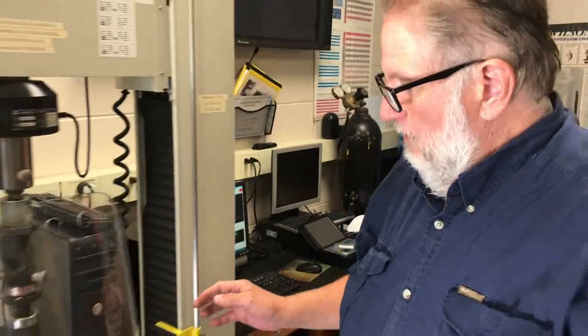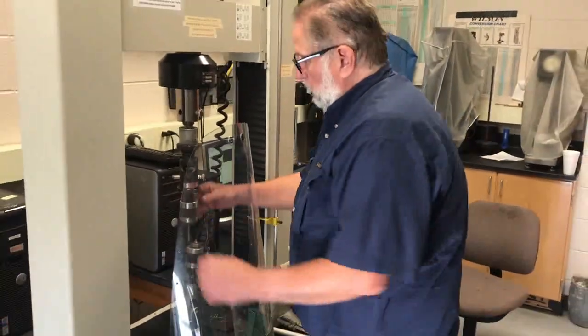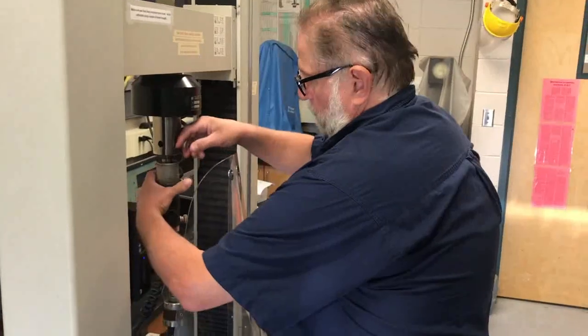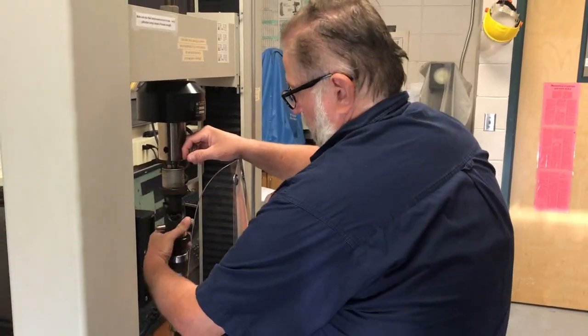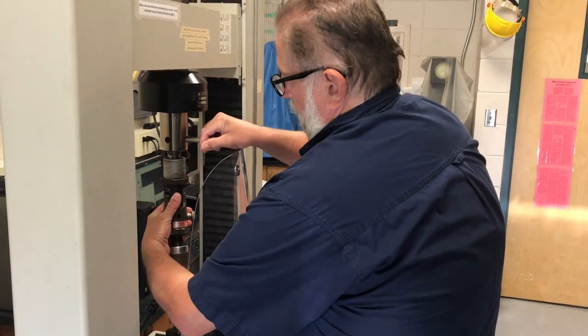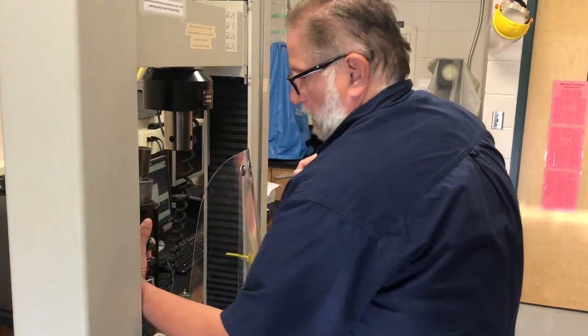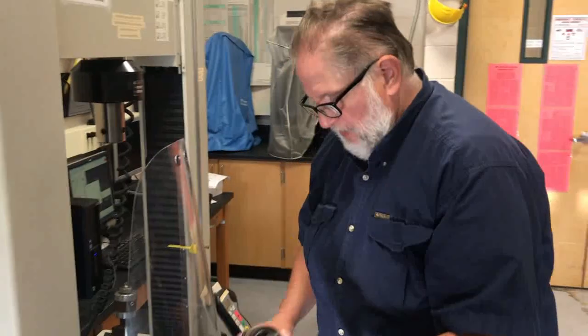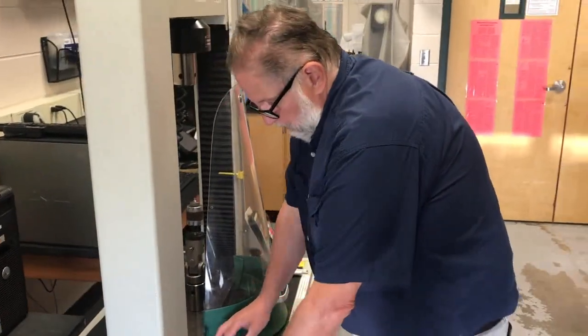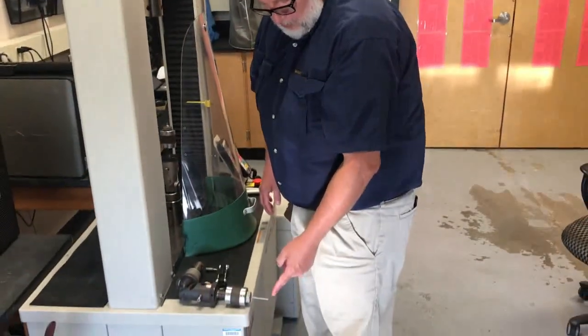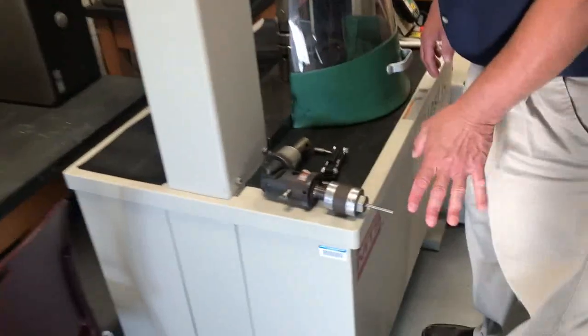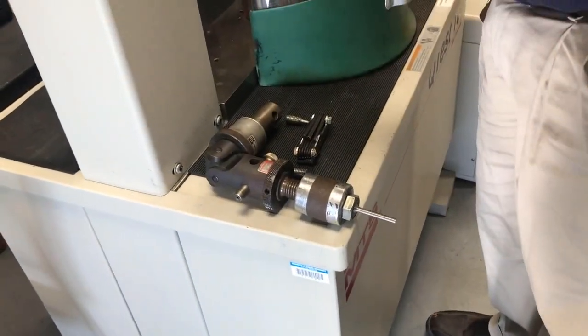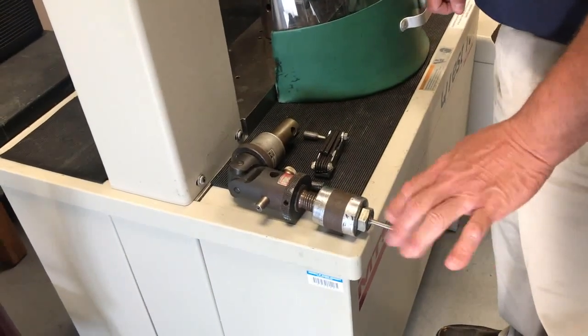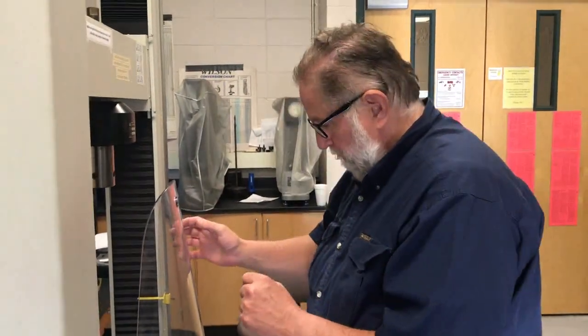So we can simply begin to remove. I would just hold carefully the rig and remove the upper part by removing the top pin between the U-joint and the load cell, and set that part aside. You want to carefully preserve the condition of your fracture surface. Don't touch it. Don't put the two broken pieces back together. Just don't touch the fracture surface, because if you touch it, you could damage it, and we can get a lot of information from fracture surfaces.